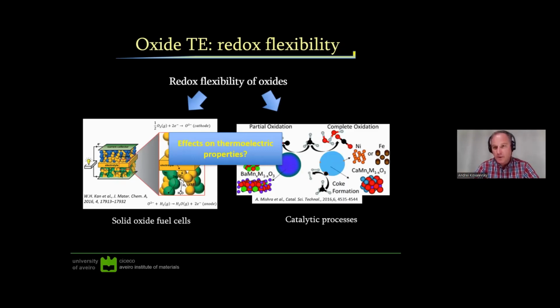But indeed, the laser processing itself, the way we use it, is not limited only to thermoelectric oxides. Whenever it could be considered possible or interesting for any other applications, it could be done. Exactly in terms of calcium ferrite, I don't see any principal limitations which don't allow growing it. For example, in the case of the 349 phase, it is difficult to prepare because it has a very narrow range of conditions where the phase is stable. In the case of calcium ferrite, I assume the range of conditions is much wider, and of course it is possible to grow.